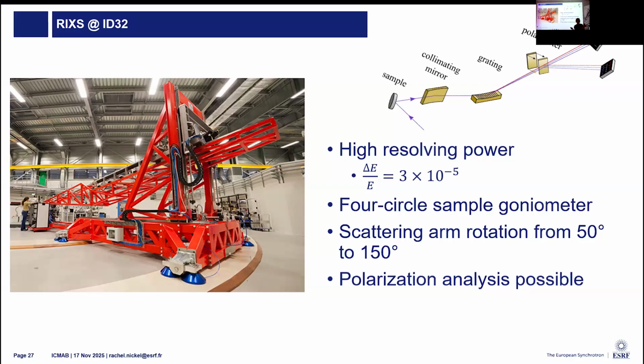It tends to be a little bit better as we go to higher energies, and at lower energies, we are often flux limited, and so we'll degrade the resolution so that we can have enough counts. It has a 4-circle goniometer inside the sample.